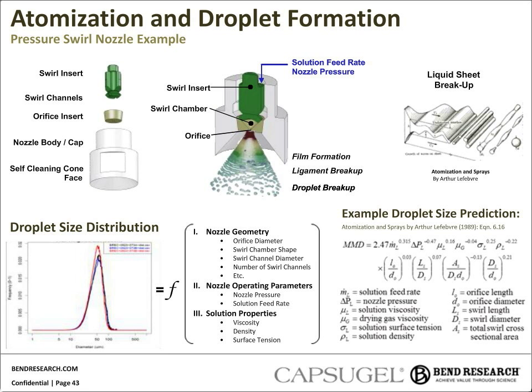Since the physics of ligament breakup into droplets is influenced by things like turbulence and instability, it can be difficult to model from first principles. But there are quite a few literature examples, entire books written with these types of correlations. And we've shown one on the right-hand side of the slide that we found to be particularly applicable to SDD droplet size predictions. And these correlations take into account the three main buckets of geometry, operating parameters, and spray solution parameters.